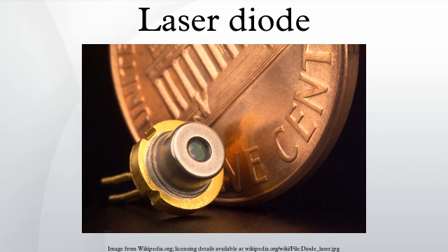Diode lasers of that era operated with threshold current densities of 1000 amperes per square centimeter at 77 kelvin temperatures. Such performance enabled continuous lasing to be demonstrated in the earliest days. However, when operated at room temperature, about 300 kelvin, threshold current densities were two orders of magnitude greater, or 100,000 amperes per square centimeter in the best devices. The dominant challenge for the remainder of the 1960s was to obtain low threshold current density at 300 K and thereby to demonstrate continuous wave lasing at room temperature from a diode laser.